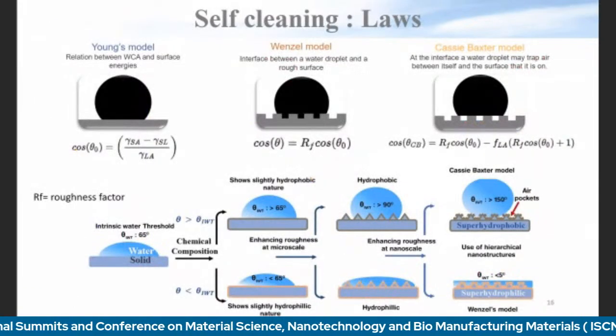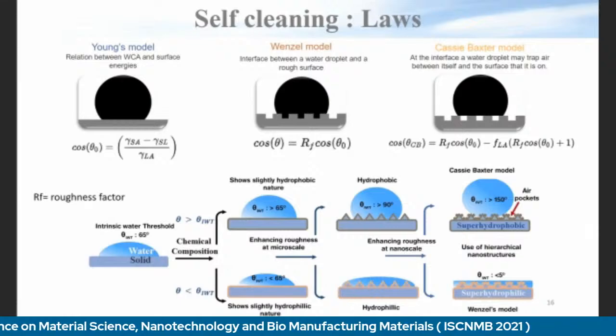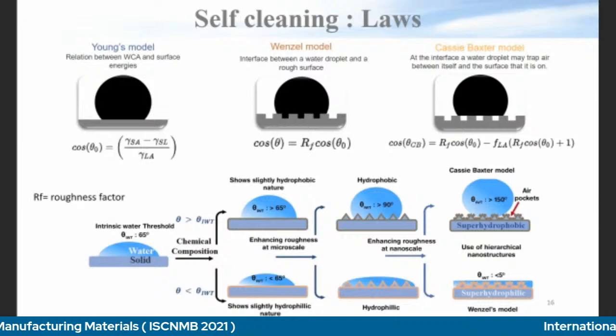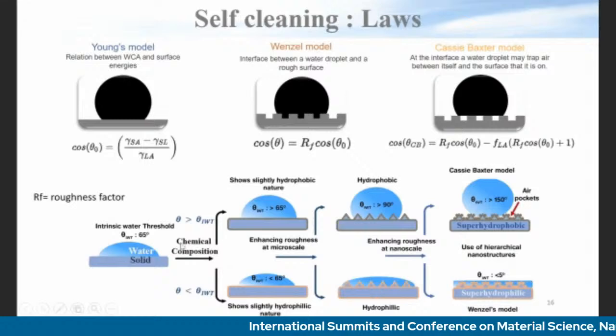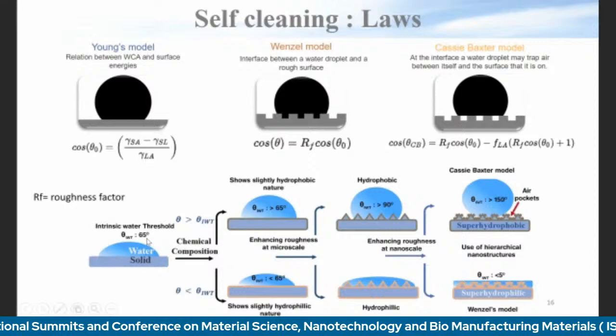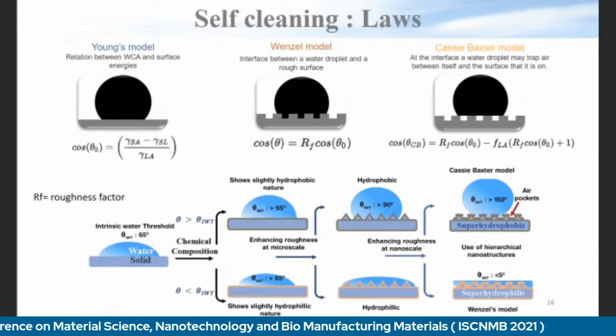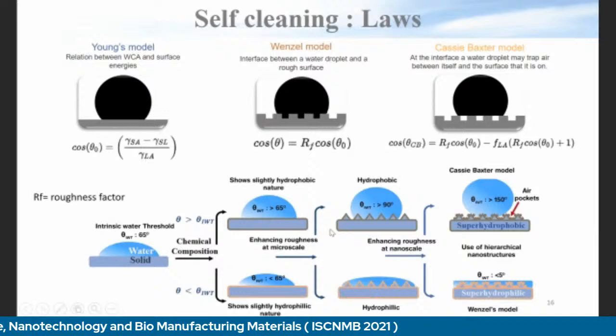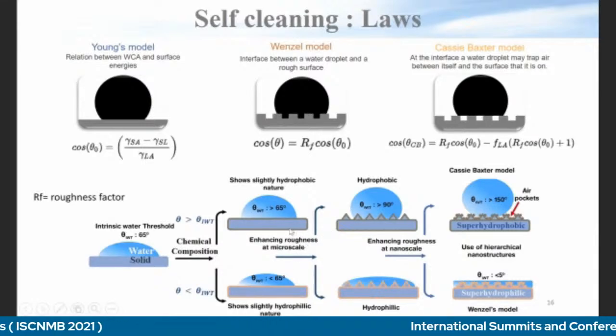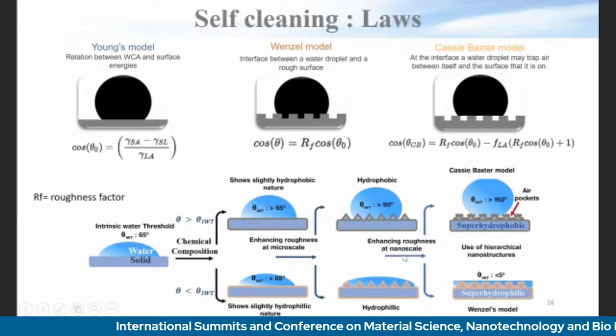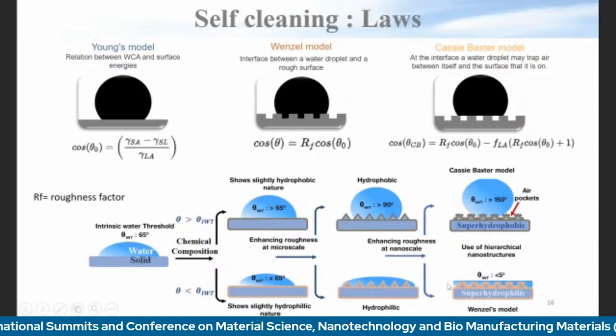These are the currently available laws which explain how the self-cleaning mechanism works. One is Young's model, one is Wenzel's, and then the Cassie-Baxter model. I'll not go in depth with all those models, but I want to explain that basically the water and glass have an intrinsic contact angle of about 65 degrees. It's not 90. Now, when you change the surface at micro scale level, depending on the type of roughness you are creating, you can have hydrophobic or hydrophilic. And when you again change the roughness at nanoscale level, you can have superhydrophobic or superhydrophilic.